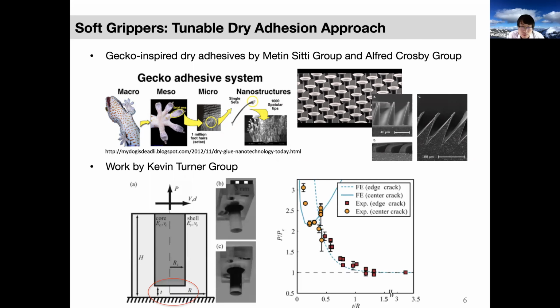More recently, Professor Kevin Turner at Penn came up with this approach. They argue that if you insert a rigid core into an otherwise homogeneous elastomeric post, you can alter the stress distribution on the interface, and that way you can alter the dry adhesion. They did both experiments and finite element analysis. They were able to identify the mechanism for the switch of dry adhesion.